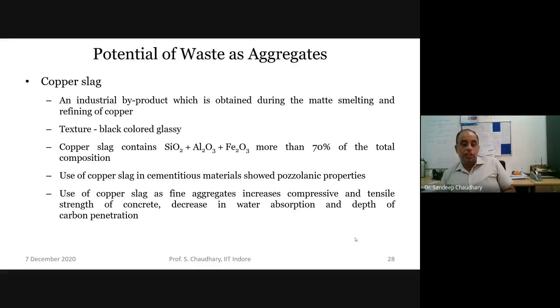And people have seen that its use as fine aggregate increases the compressive and tensile strength of concrete, and decreases water absorption and depth of carbon penetration. And we know this is also an important aspect, depth of carbon penetration, because the corrosion is not directly taking place as such. That's related to the carbon penetration, because it reduces the pH near the reinforcement. So it's not that finally we have to look for the corrosion. We have to first look for this carbon penetration.